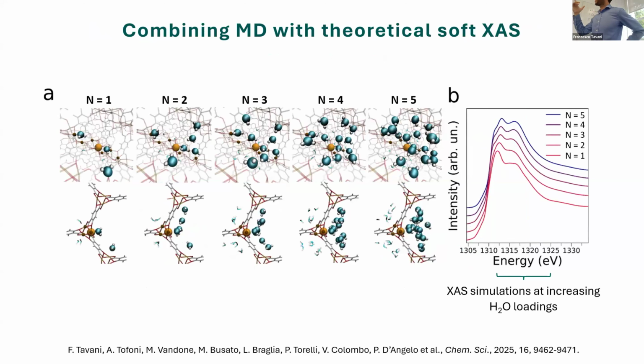So we can, again, track the progressive population of the local structural environment of a selected magnesium site by water. For example, at a loading of 1, 2, 3, 4, and 5 water molecules per metal site, and then calculate the corresponding soft XAS magnesium K edge. So this is the magnesium K edge, I forgot to mention that before, which is located at about 1,300 eV. So we calculated the soft XAS curves based on the molecular dynamics snapshots.